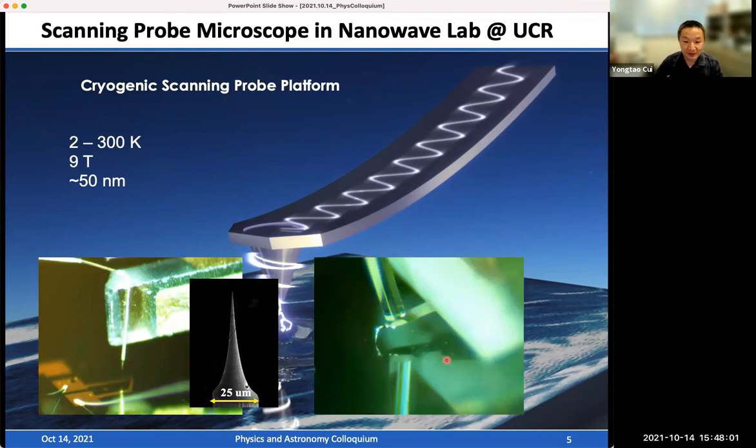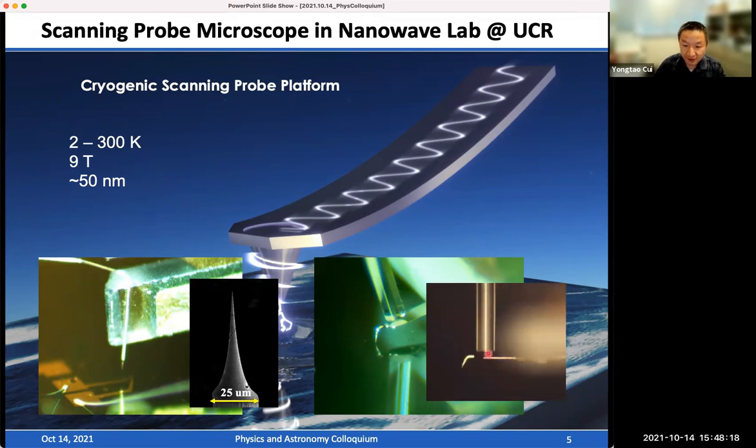So we sometimes use a more flexible probe, a probe with a cantilever. This cantilever is softer and it can bend when it's touching the sample. What you see here is a side view where we position an optical fiber against this cantilever. Between the two surfaces, it simply forms an optical interferometer, which is very sensitive to the length of this cavity. That's what we use to detect the tiny deflection of the cantilever. From that, we can learn about the forces applied on the cantilever.